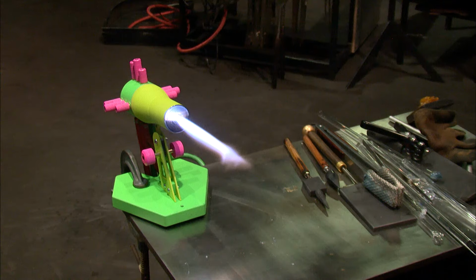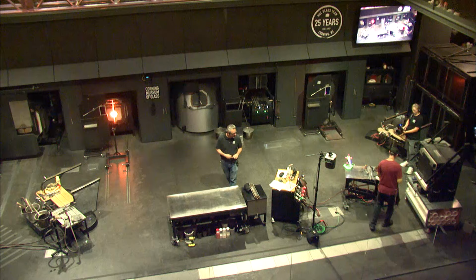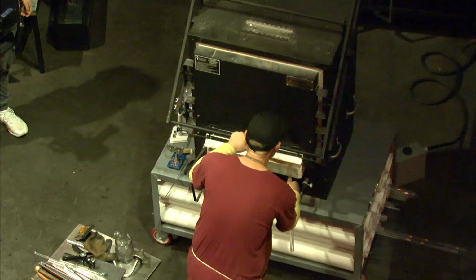It's 5 minutes. All right. Yeah, so Yush is pointing out for annealing, it's 1 minute per millimeter of thickness. I would say that's more for reheating and feeling the pieces stable. Annealing more, maybe 5 minutes per millimeter of thickness. But yeah, as far as feeling safe about pulling that piece out, a minute per millimeter is probably pretty smart. That makes sense. Yeah, so we had determined annealing times based on the composition of the glass, what ingredients are in it, and also how thick it is at its thickest point. We want to make sure it cools perfectly evenly from surface into core.